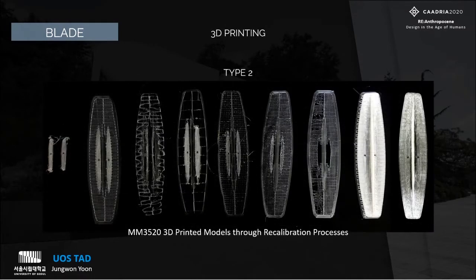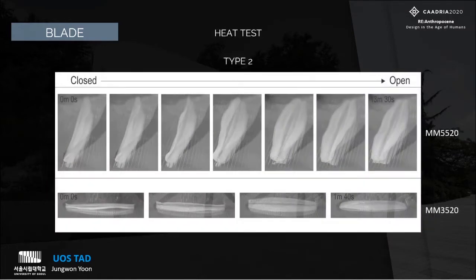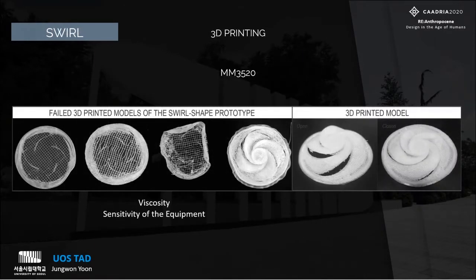In 3D printing with the MM3520, many recalibration processes were taken to achieve the successful setting. Also, in the heat test, the MM3520 showed much more prompt response to the temperature and quicker shape changing. From this experiment, we can secure the 3D printing setting of our 3D printer for MM3520. For the more complicated type, SWIRL, we also conducted a series of trials for 3D printing.